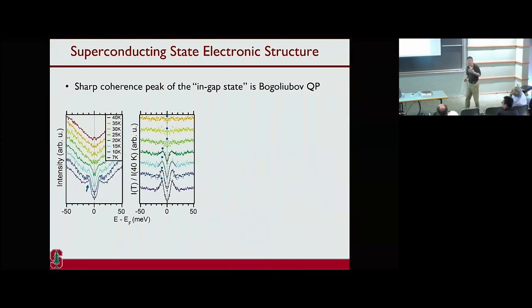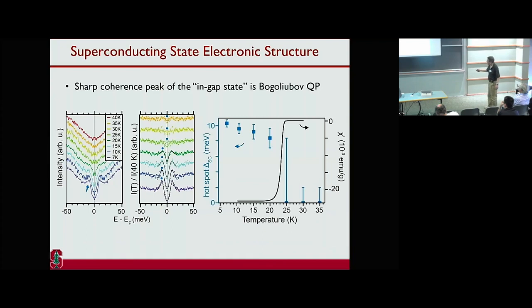Now, by seeing the Bogoliubov quasiparticle, now you can use the technique. You don't have to use the leading edge as we were struggling earlier. Now you can see the peak in this case, and you can have a better sense of the superconducting gap. That's the transport, and you can see the peak turn on at TC, and that, of course, we now can say is the superconducting state.